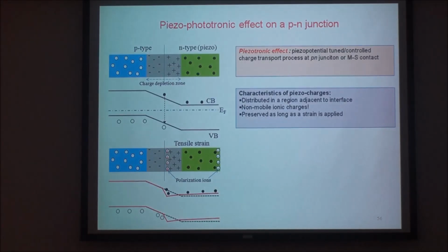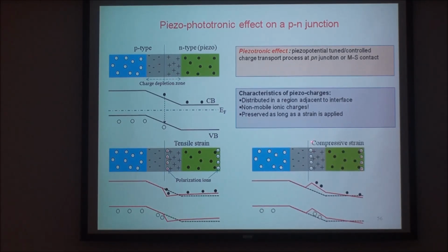If you have a p-n junction, this is a p-n junction here, same thing. If you have a local ionic charge introduced by the piezoelectric effect, it gives you a little dip here, and this could trap electrons momentarily and could enhance LED performance. If you have a negative ion, it gives you a little bump, and that can also affect the charge recombination or separation. I will use two examples to illustrate this. One example is the solar cell, and one is the LED. One requires charge separation, the other requires charge recombination.